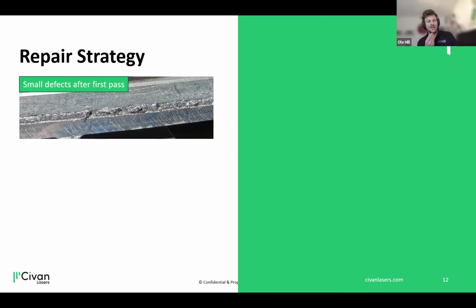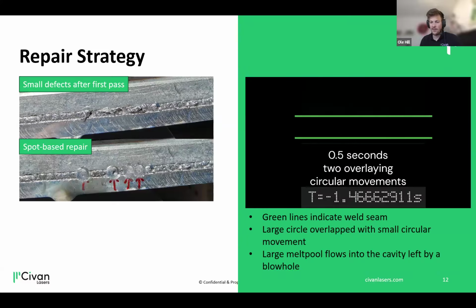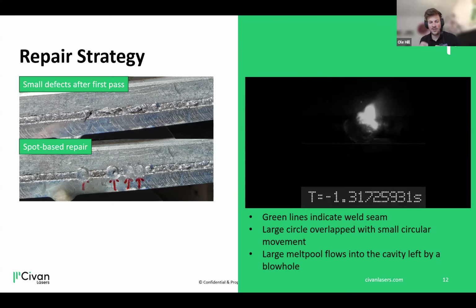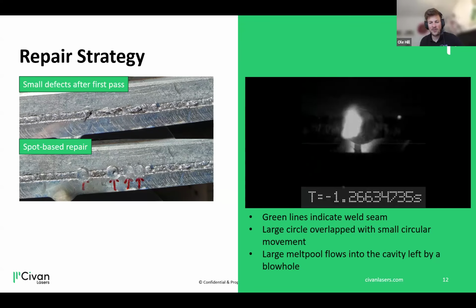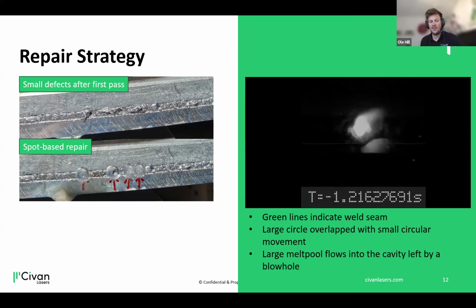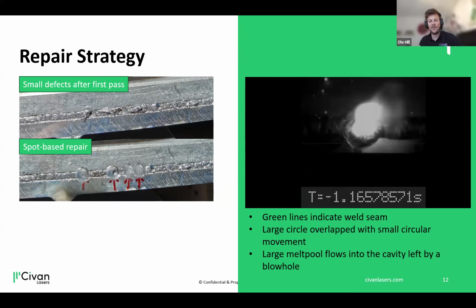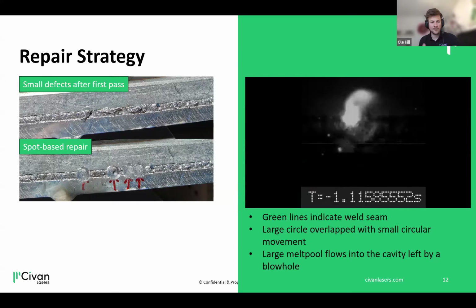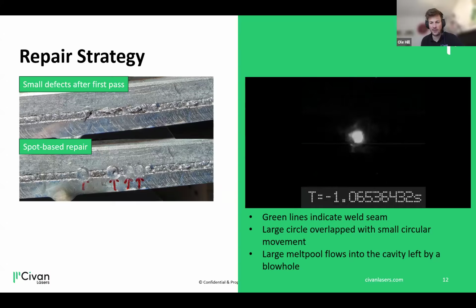And here in the upper picture, you see a weld seam that had a small series of blowholes, which resulted in this rough surface, and also a bit of material got thrown away. But by doing a spot repair, we could close all of these holes. And on the right, you will now see a high-speed recording of this process as well. So the idea was to create a very large, it's just a few millimeters, but quite a large melt pool, which allows enough material that is basically next to the blowhole to melt and flow into the cavity that was created by the blowhole.